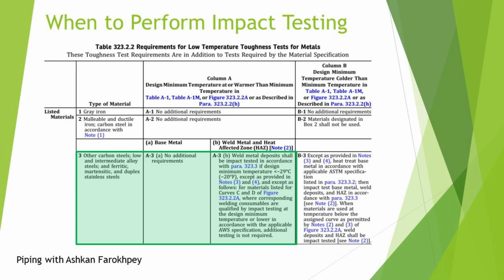According to the third row, using all the rest of carbon steel, low alloy steels, ferritic, martensitic, and duplex stainless steel materials is allowed, but under some conditions. As is indicated in column A, if these materials are going to be used in temperatures warmer than their minimum temperature of table A1, the base material doesn't need to be impact tested, but the weld metal shall be impact tested if the process design minimum temperature is colder than minus 29 degrees centigrade.